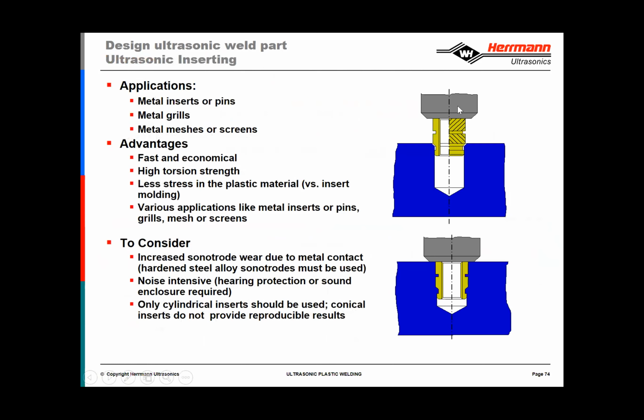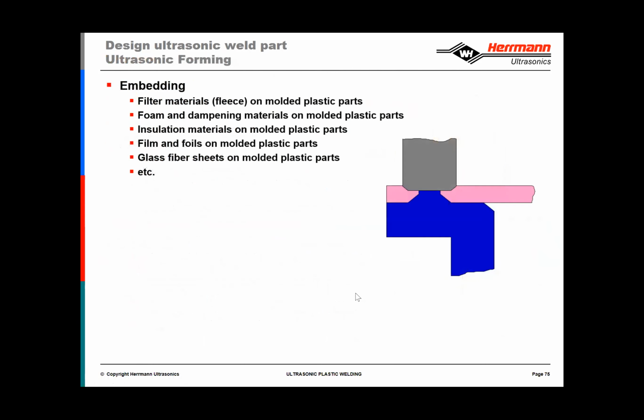So the sonotrode, again, hardened steel because we're making metal-to-metal contact. The sonotrode heats up the threaded brass insert, pushes it into the plastic part, and the plastic part's hole here is smaller in diameter than the size of the insert. And the intent is that the molten material of the plastic flows into and is contained or trapped within those flutes and cuts and knurls, and to provide the retention to accept a screw for disassembly.